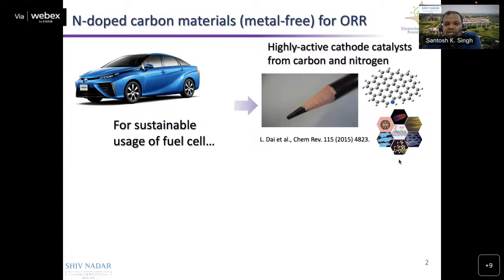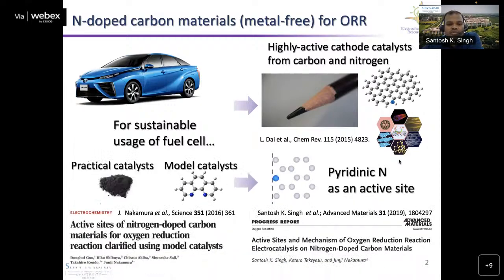That mystery was solved by Nakamura et al. group, where they prepared model catalysts in which they exclusively doped pyridinic nitrogen, pyrrolic nitrogen, and graphitic nitrogen in graphite, and they clarified by electrochemical studies that the pyridinic nitrogen is basically responsible for the higher activity. So if you want to develop a catalyst based on nitrogen carbon materials, the carbon materials should have a higher amount of pyridinic nitrogen, so that we can get higher activity.